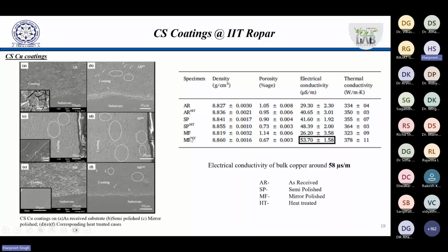And we were amazed to see that in this particular case, we got very good adherence for mirror polished samples. This is another thing about cold spray. In certain cases, it is good to have some roughness, but in certain other cases, it's good to have a mirror polish. Whereas in thermal spray processes, it's well established that roughness is the driving thing there because there is only a mechanical keying effect. But in this case, the requirements of surface finish change as we change the set of materials, meaning the material to be coated and the powder material, substrate as well as the powder characteristics. When they change, the roughness requirements also change. So in this hard on soft contact, we saw that mirror polish is working well. Why it is working, I'll come to that also.